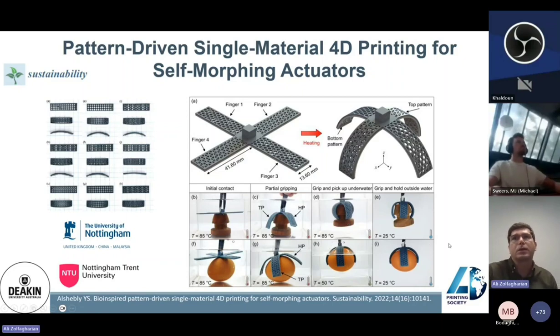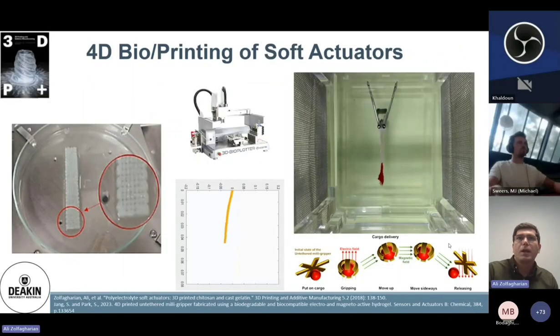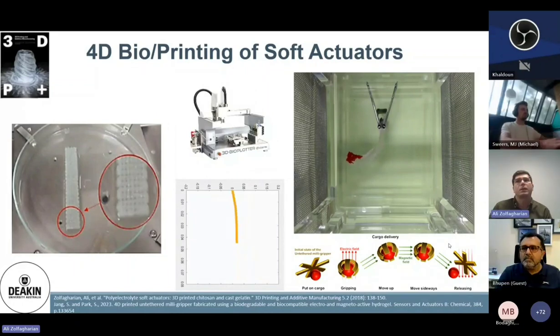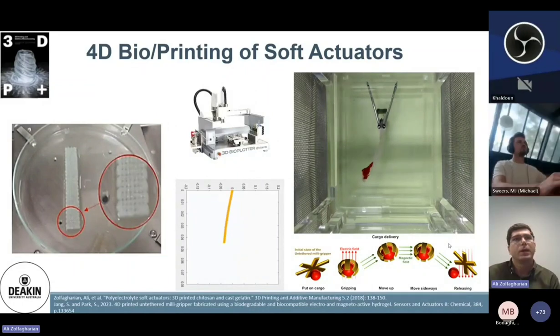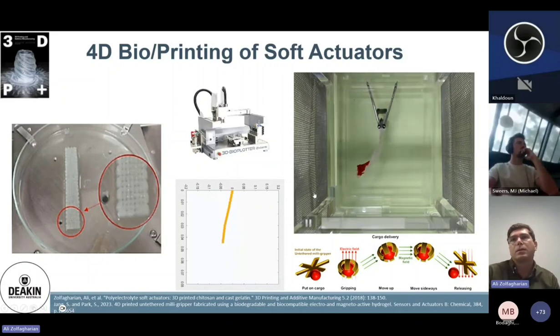This is still based on the 3D printing or 4D printing processing parameters and the shape memory polymer behavior of the materials used. And this is another work that, during my PhD, we came up with, using polyelectrolyte hydrogels. We 3D printed hydrogels, particularly chitosan at that time. And then the optimization was quite burdensome. We needed to come up with some coagulation after the printing, and also optimize parameters like the pressure and speed of the nozzles. And the physics behind that was multiphysics.